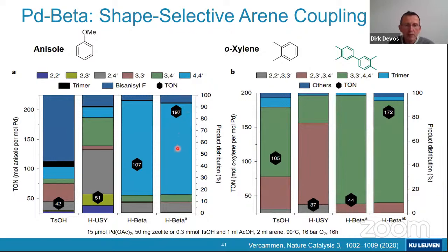If you compare, for instance, what happens with paratoluene sulfonic acid, then we see that with the paratoluene sulfonic acid, we got a byproduct, bis-anisyl. If we try to couple anisole to bianisyl, then we get the bis-anisyl F, which means that actually the methoxy group is decomposed and starts to bridge with a methylene bridge between 2 of these arene moieties, which is not what we desire. So indeed, again, the beta catalyst is a quite superior catalyst.